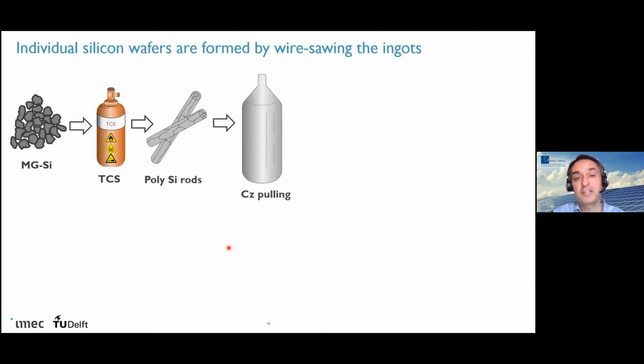Now, once we have this ingot, typically the top and the bottom and the sides of the ingot are removed, because they contain lots of impurities and do not have controlled doping densities. So we actually use only the center part of the cylinder.